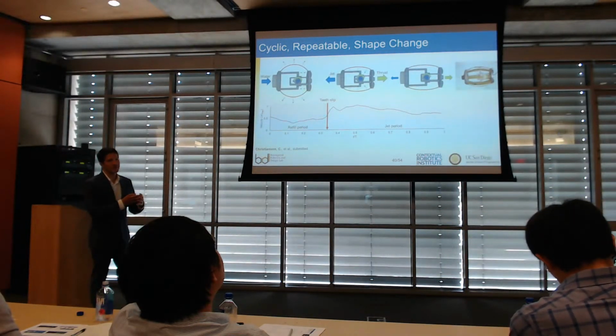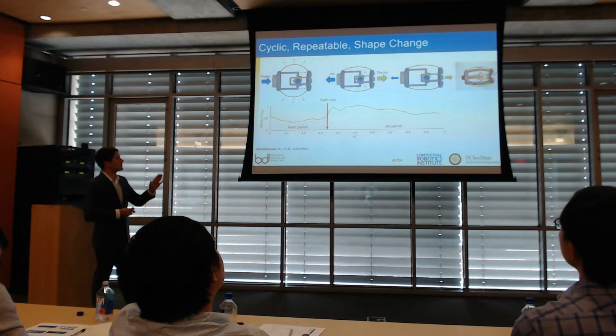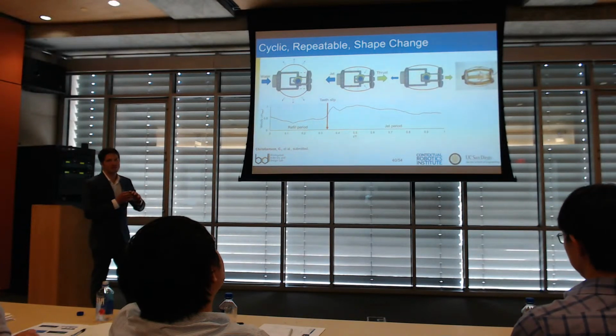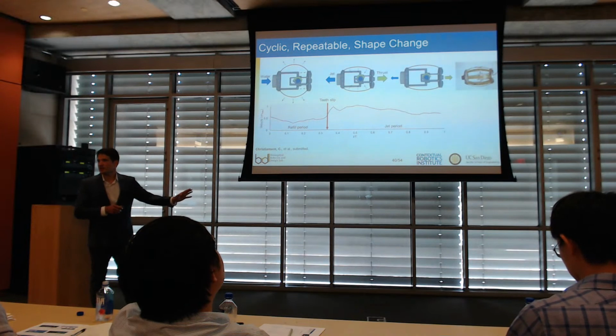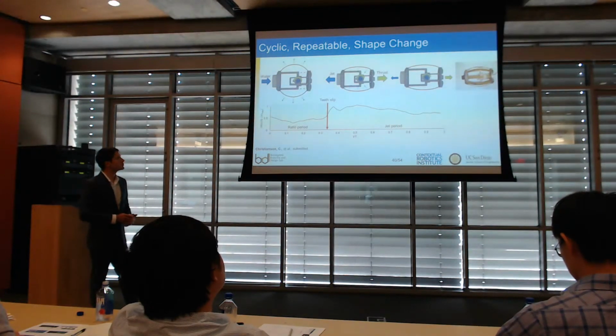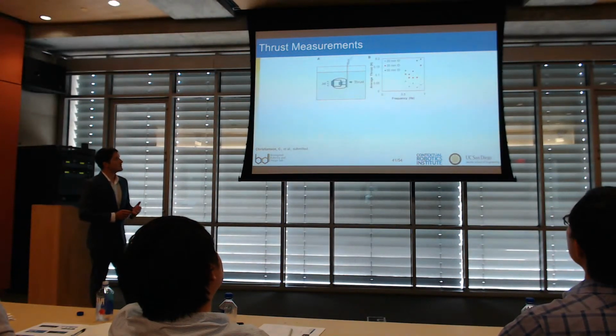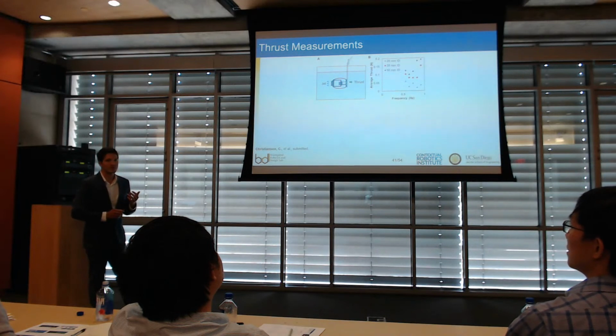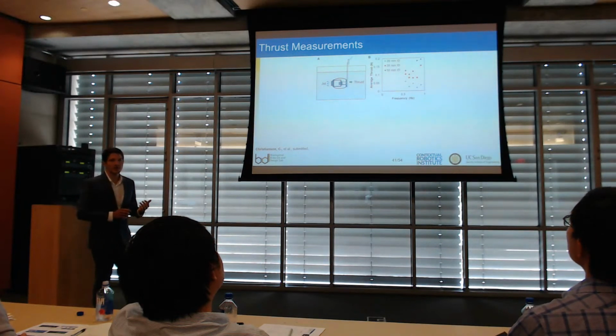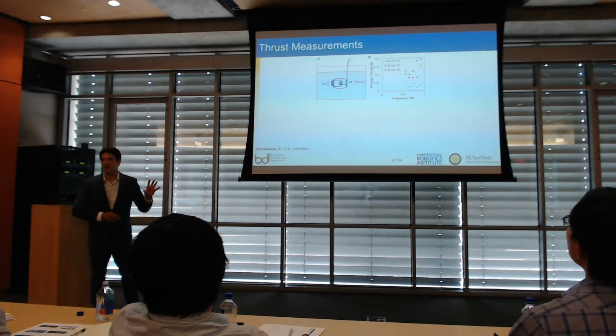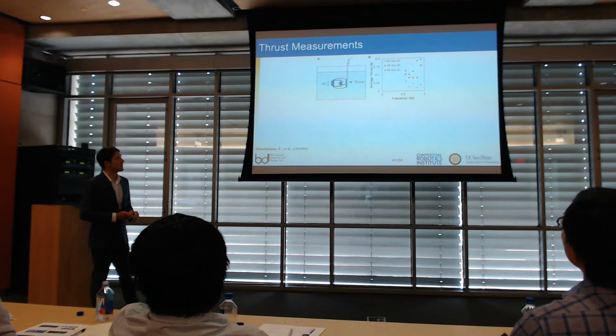And so during the refill period, it's slowing down as it's sucking in water, and then once the teeth slip, it starts shooting out the water and begins accelerating. We wanted to see if we could measure dependence on thrust for formation number. And so we tested it by putting the robot on a load cell to measure the amount of force that we can get out of it, and then tested it at different frequencies and for different nozzle diameters.